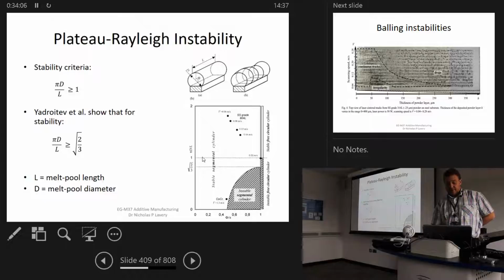And what you can see on the bottom right-hand side there is areas of instability for different velocities with different steels. You can see with steel, you've got quite a large area of very stable melt tracks. But when you're dealing with different materials at pretty similar velocity, you can have a very different result. So you can have a lot more balling from this type of material than the other. A lot of that is determined by properties of the liquid metal.